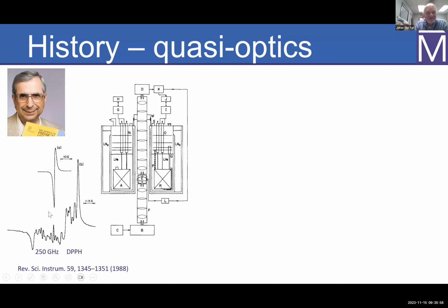And you can see one of the results in the original paper, DPPH at 250 gigahertz, which was really a high frequency at the time. So from X-band to 250 gigahertz, it makes a difference. If you have single crystals of DPPH, and they're oriented slightly differently, these are all exchange narrowed lines, but still, because of the g anisotropy, you do get some distribution of these g values which you didn't see.